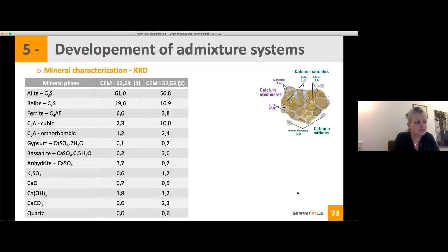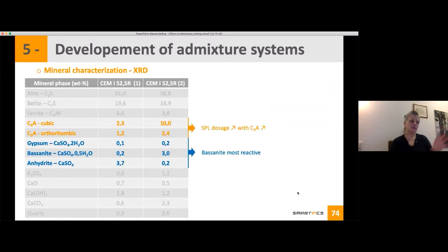So what do you see here if you look at the aluminate? There is an increase in C3A between the first CEM I and the second one, and the increase is very high. Yeah, combining both the ferrites and C3A, I think it's higher in the second composition. So one of the first things we are looking at is C3A content and also your sulfates. And why is that?